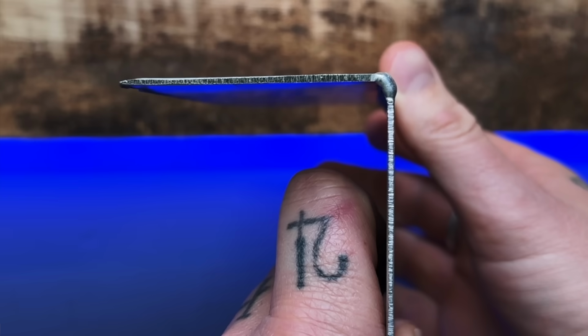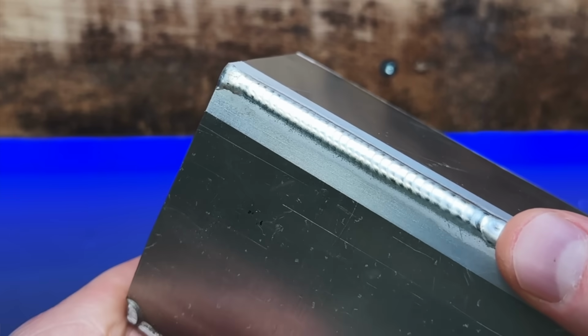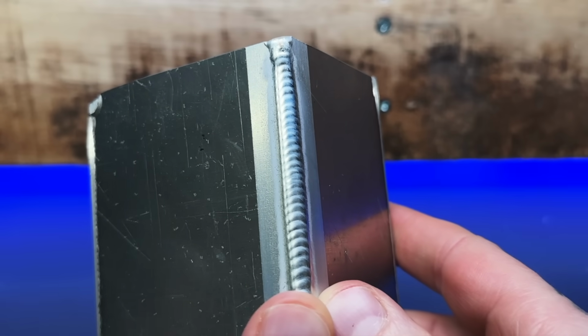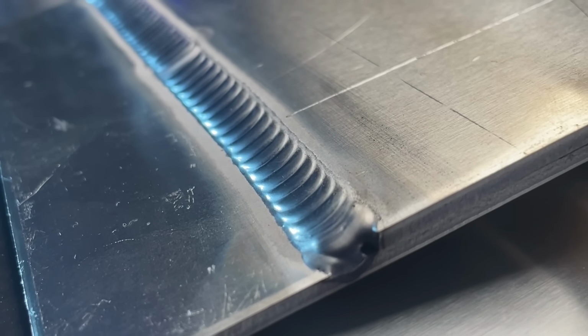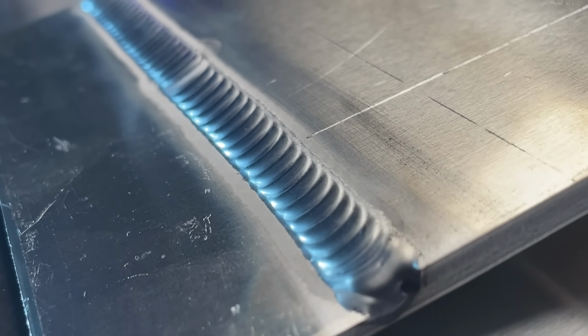Now, at low amperage, with a really properly prepared tungsten, this arc is gonna snap up and establish really easily. When we start out, we do not want the arc to be wandering around. Sometimes at low amps, it's common to see the arc kind of flickering from side to side. We want things to specifically lock on and establish an arc on exactly what we are aiming at. Especially like this one that we looked at already, the outside corner joint with relatively thin material. If your arc is jumping from side to side when you're trying to get started with something like that, this is going to give you a really frustrating and terrible start to your line. And we just talked about how important a proper start is.